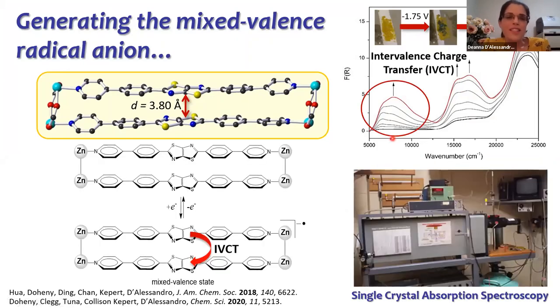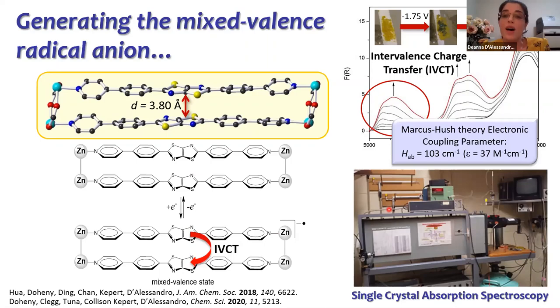And after a great deal of work, what we were able to reason was that this was due to a through space intervalence charge transfer process. And using single crystal absorption spectroscopy, so this is just a single crystal of the MOF that we can perform absorption spectroscopy on, we're able to use some various theories, Marcus Hush theory being one of the most predominant ones, for being able to understand more about electronic coupling. And I won't labour this too much, but this HAB parameter is a very important parameter because it tells us something about the relative extent of coupling. So here we find a value at just over 100 wave numbers, which is relatively low and suggests that that radical is relatively localized on one of the thiazolo-thiazole ligands.